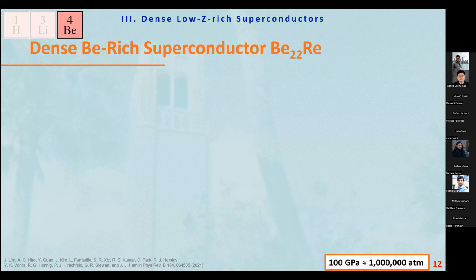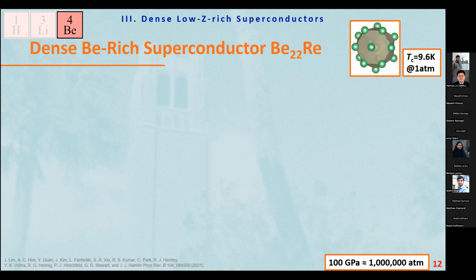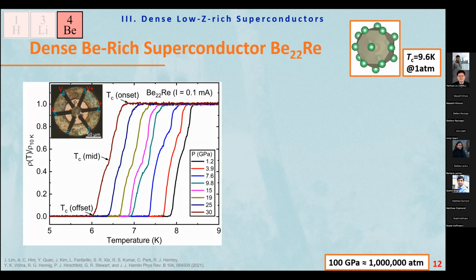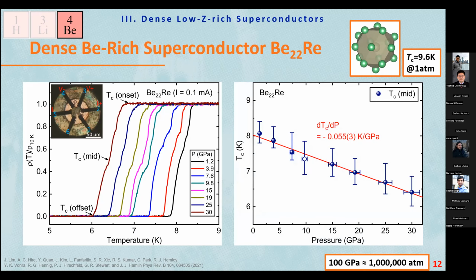So we made the beryllium 22 rhenium compound and tried to squeeze this sample. And an interesting part is that this one also has a cage-like structure, with beryllium surrounding rhenium. And even better, it is an ambient pressure superconductor. So TC is a relatively high 10 Kelvin at ambient pressure. So we don't need pressure for this one, but we hoped that when you squeeze, TC would increase like the hydride, but the surprise is that it's the opposite. So the pressure kills the superconductivity in this case.